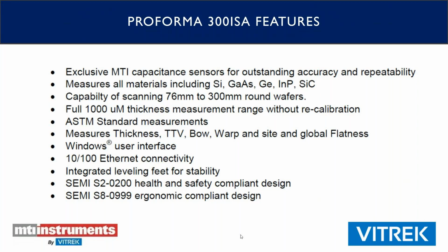You can actually measure thicker wafers than this with probe adjustments, but the measurement range, the variation is up to basically a millimeter in thickness variation there. So it does meet all the ASTM standards.